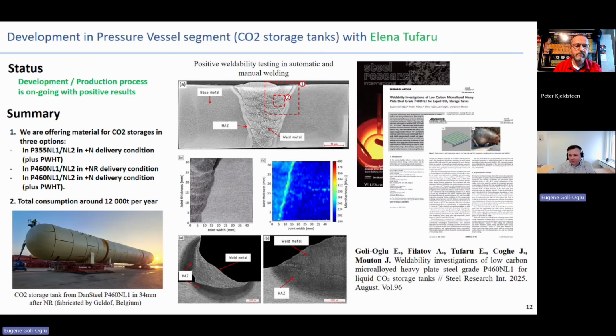And then we also see the tendency that if it's installed on land, for CO2 capture or temporary storage or long-term storage, then it will be P355, thicker wall. But for example, if it is for transportation, then it's more interesting to have a higher strength grade and a thinner wall, and then your construction will be lighter as well.